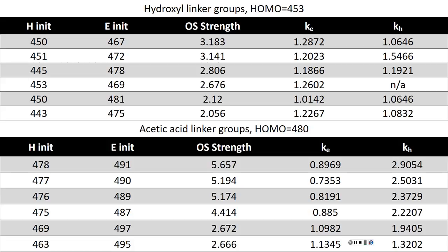So it also depends on the energetics of your excitation, and this again probably depends on the band character, orbital character, where you excite. Let's say if you excite 450, 481 with the smallest rate for the electrons, I don't know actually which system you excite. You excite the perovskite? This is the analysis of where initially you excite the system. Are you exciting perovskite? Are you exciting the titanium dioxide quantum dot? Probably not, because your quantum dot should have a very large band gap, right? You should not expect some excitation on the quantum dot. Or maybe, yeah, if your orbitals are very hybridized, then you excite some kind of charge transfer, which is not really charge transfer because of the very strong hybridization.